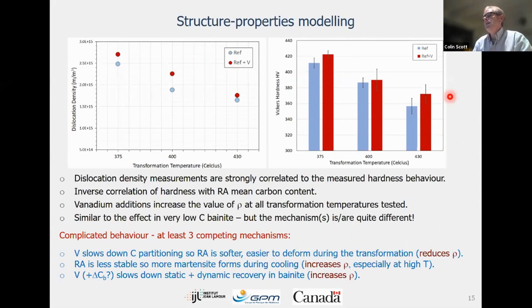So what we can say is that dislocation density measurement strongly correlated with the measured hardness behavior. That's obvious. We have an inverse correlation of hardness with the mean carbon content in retained austenite. That's very interesting. What we also can say is that the vanadium additions increased the dislocation density at all the transformation temperatures tested. This is a similar effect to what we see in the very low carbon bainite steels, the X80 that I showed you at the beginning. But the mechanism is not the same. It's not because we're delaying the bainite start. It's quite obviously not the case in this study.